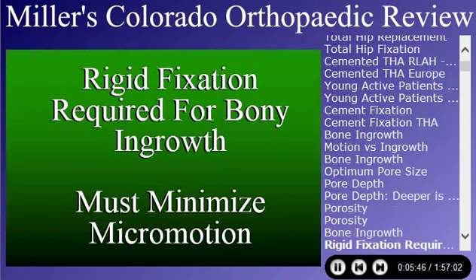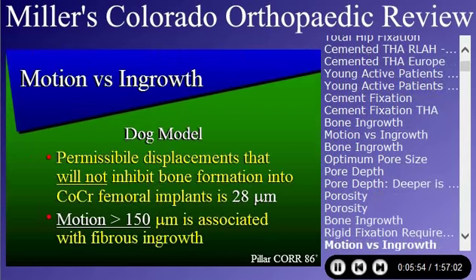I stress this, rigid fixation is required for bony ingrowth. You've got to minimize that micromotion. Pillar showed that the permissible displacement that would not inhibit bone formation was 28 microns, and you got 100% ingrowth. If you had motion greater than 150 microns, you got fibrous ingrowth. So you really got to wedge these implants in there tight, so the bone will go into those pores. So the bone cells can't see a moving target. So that's why non-cemented fixation tends to be a little bit more demanding than cement.